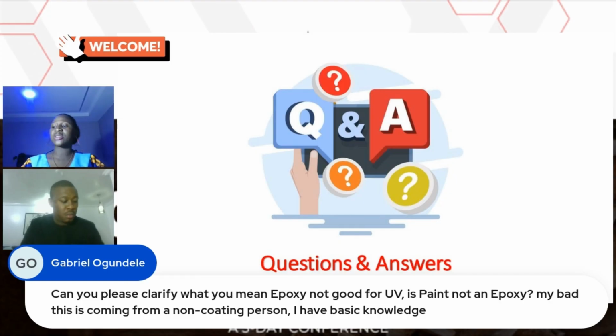So what it means is that you can do an epoxy based primer for those who still do three coat system. You can do an epoxy based primer. Perfect. Your system is protected. You can do an epoxy based intermediate coat. Oh, you have reinforced the system and you are using an epoxy based finish or top coat. See, your system will be protected, but then you're likely to see dull surface in a very short time, especially if you're exposing the system to sunlight. So epoxies are not good for UV light.